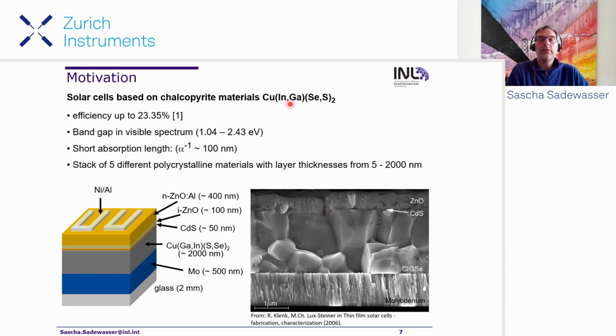And by varying the indium and gallium composition or the sulfur and selenium composition, you can cover a very wide spectral range. So you cover the full visible spectrum, which of course is quite useful for making solar cells out of this material. And so far the best efficiency on the laboratory scale has been achieved with 23.35%. And this is very competitive, of course, also in comparison to silicon photovoltaics. It's a fairly complex stack of 5 layers and some surface treatments that are required during the fabrication. The most important part is this polycrystalline layer here with grain sizes on the order of about 1 micron of this copper indium gallium diselenide.